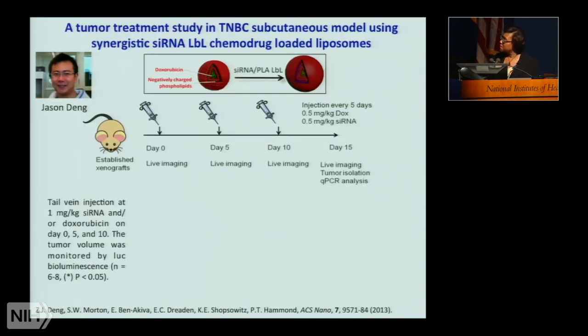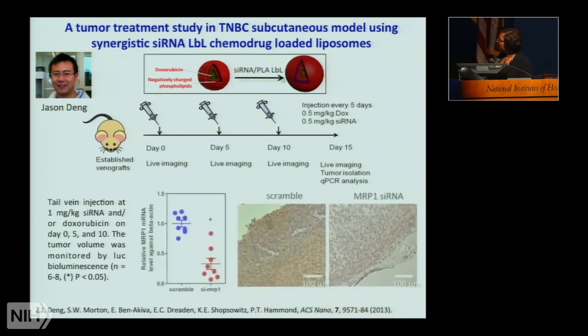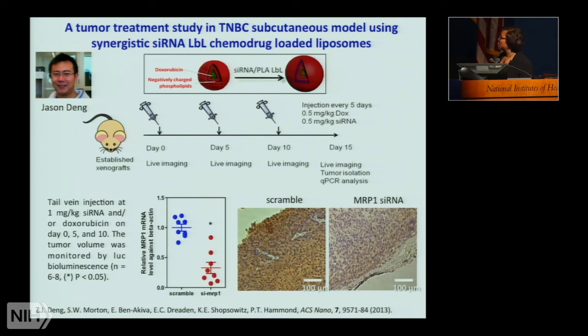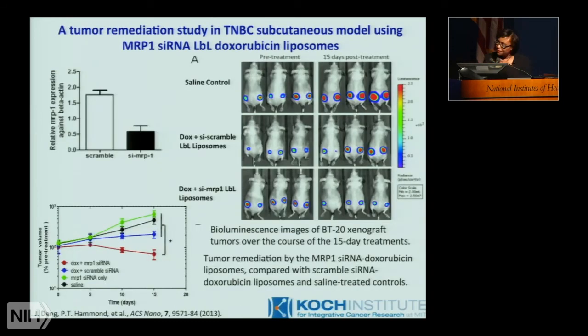killing tumor cells. In this work by Jason Deng, who was a postdoc in my lab, we looked at a series of injections in these animals, which contained xenografts of a triple-negative breast cancer. We found that we were able to get significant knockdown after treatment. Here we're looking at tumor sections that were stained, and here we're looking at PCR, which shows that there is a roughly 75 to 80% knockdown of MRP1 in these tumors.